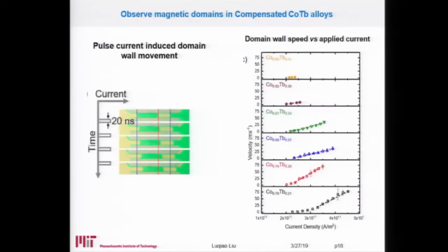Yeah, since we did the experiment in this kind of multi-domain device, it has a very long propagation distance. To realize micrometer movement, we have to apply nanosecond pulses. So it's not terahertz. No. Another reason these materials are not extremely fast is that there is terbium inside, which is a rare earth, and rare earths usually have very high damping. That also lowers the speed of the magnetic switching. Based on a simple argument, if you can make a nanometer-size device out of those materials, I think the switching time will be around or below 100 picoseconds. But we just didn't make that type of device. Thank you.